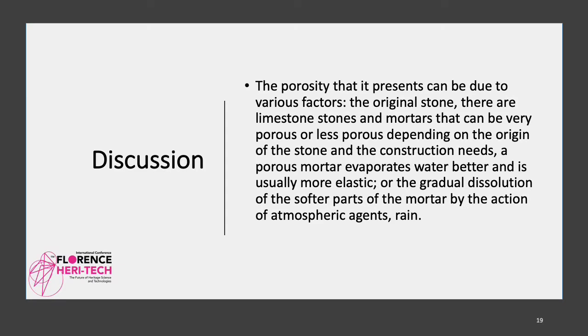The porosity that presents can be due to various factors. The original stone. There are limestones and mortars that can be very porous or less porous depending on the origin of the stone and the construction needs. A porous mortar evaporates water better and is usually more elastic, or the gradual dissolution of the softer parts of the mortar by the action of the atmospheric agents, rain.